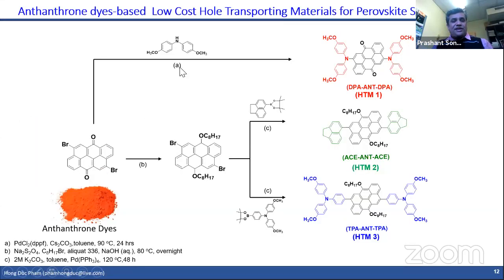So first we took up this dye, and we end-capped it with a diphenylamine. This is commercially available; we synthesized the diphenylamine with the methoxy-substituted one. And then we used another end-capping group, a dimethoxy-substituted triphenylamine with the boronic ester. So the boronic ester with the bromine combination is called Suzuki coupling. Once boronic ester and bromine are combined together, that is the Suzuki coupling protocol. Whereas an amine group attached to the bromine is called Buchwald coupling. We can make 3 compounds out of this starting material. So initially we just reacted this material with this, and we got HTM1, then we got HTM2 and 3 by using this end-capping group.